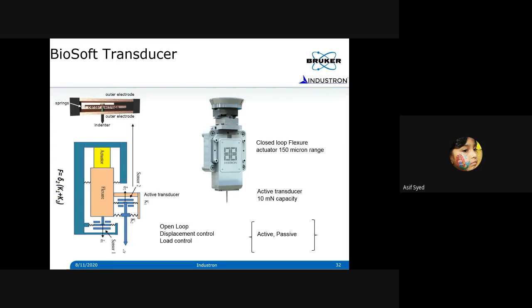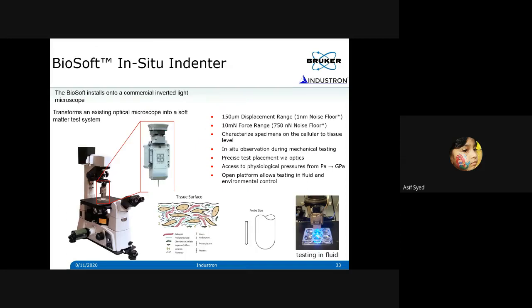Using this trick, we were able to build this transducer, and it can be put onto any optical microscope. This is how we were able to extend the range in terms of displacement, without losing the force sensitivity of the transducer. This is what we call the BioSoft Transducer. And as I mentioned, you can put it on an optical microscope. On top of it, you can also change the type of probe, because this is just a screw mount. You can unscrew it and put a different tip, so you can have a different type of probe.